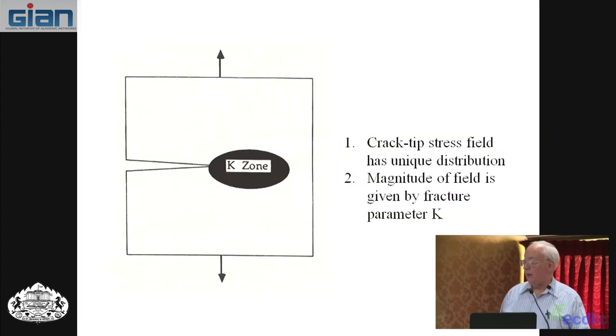In doing fracture mechanics then, people look at the area around the crack tip as a black box. Because there is a unique distribution, there is a zone around the crack tip characterized by K that tells you what's going to happen. That zone is not given a size, but just as the area around the crack tip, and the magnitude of the field then given by K, and the magnitude of that field tells you what fracture you would get, whether you're going to have fracture toughness, failure, fatigue failure, or environmental effects.